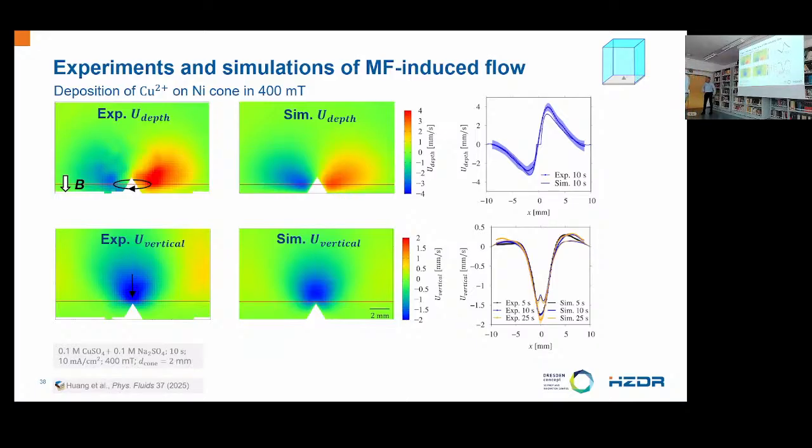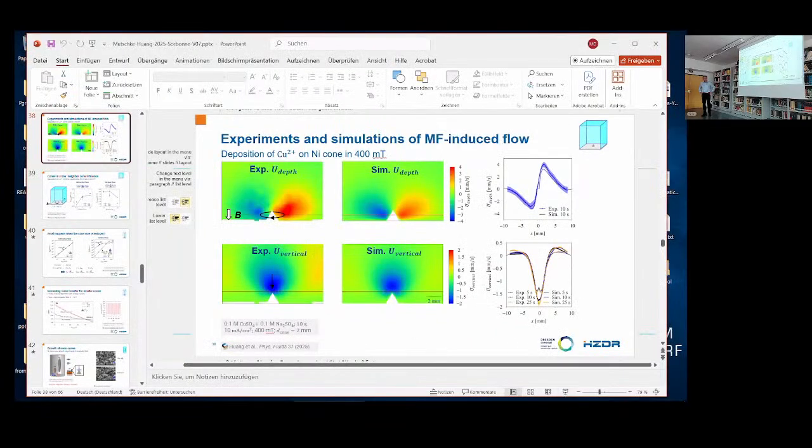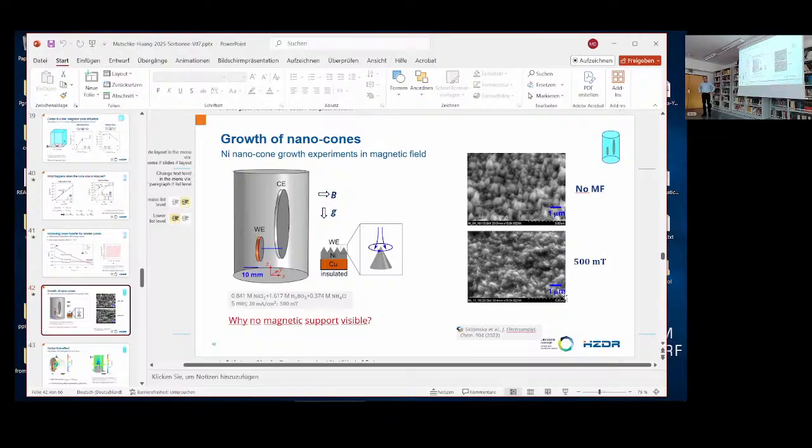Other questions for Mengyuan? Yes, Wei. I see that you could manipulate the production of the nanostructure, the nanocone. I see that the typical diameter of the nanocone is 70 nanometers. So how do you manage to control this diameter of the nanocone? Yeah, the 70 nanometer is in the work of Katharina Brinkert, and in our experimental collaborators, I remember it is some 100 nanometer size, and in this, we don't really control the bottom side of the cone. So the capping agent is added, and then with this initial roughness that I said before, when the surface is before the deposition, I think this initial roughness is determining the basic size of the cone. Usually they are in this size scale.